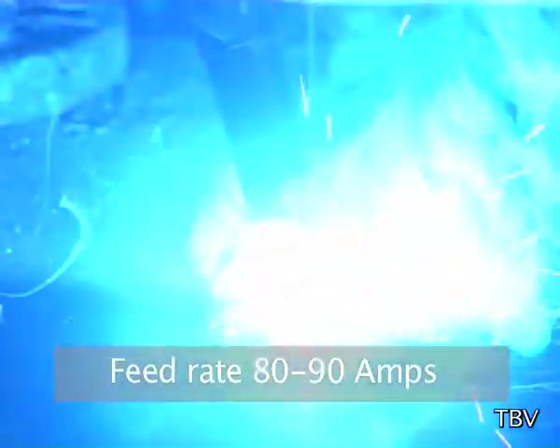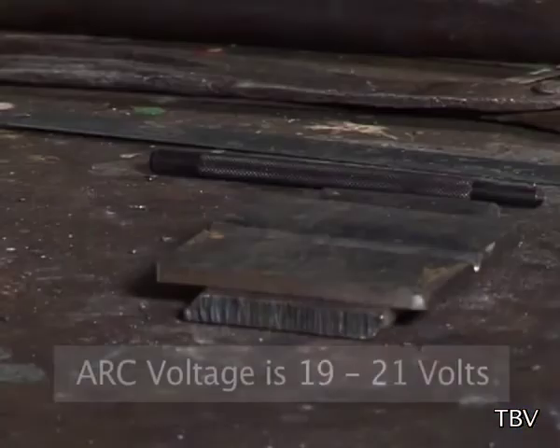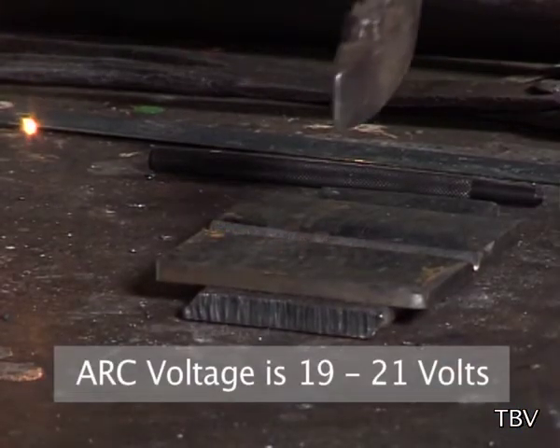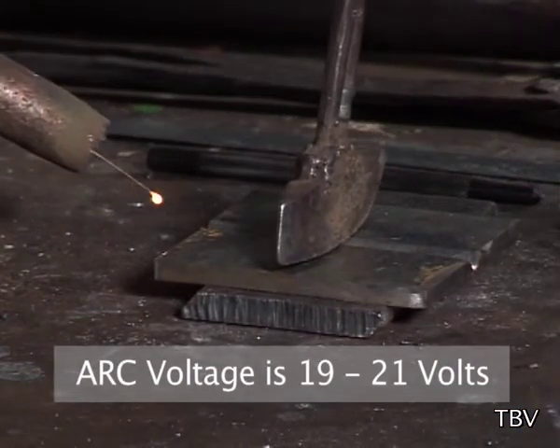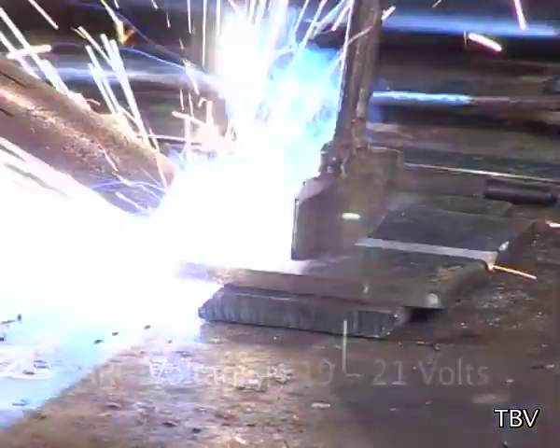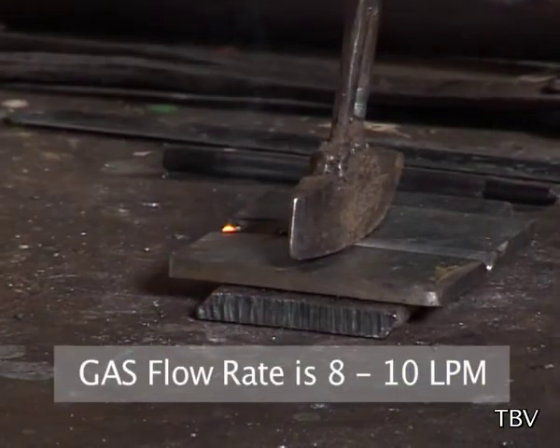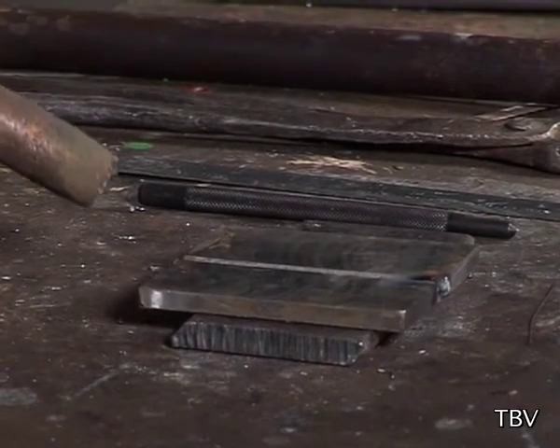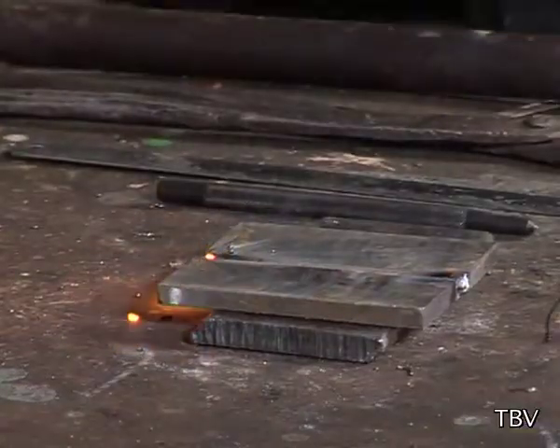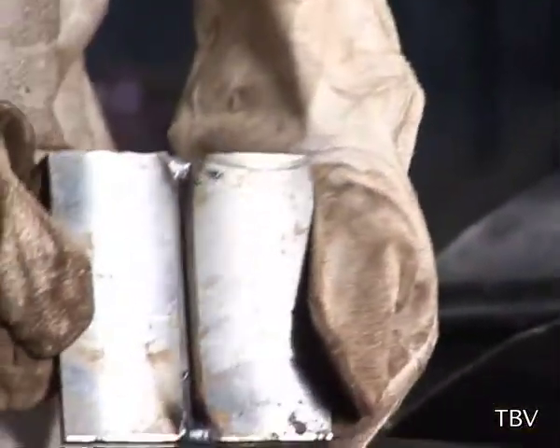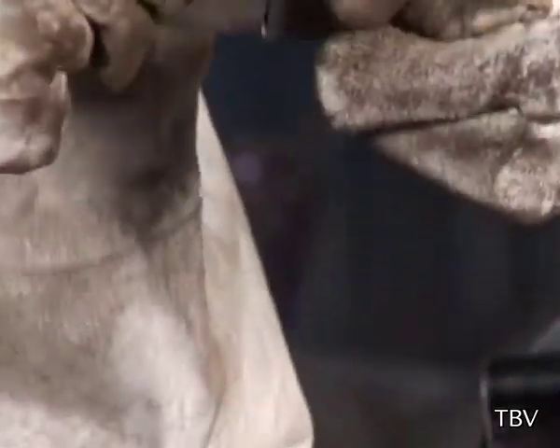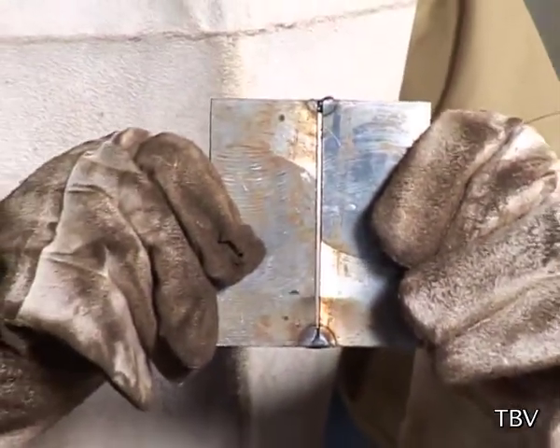Set the feed rate. The arc voltage is set at 19 to 21 volts as required for dip transfer mode. The gas flow rate is set at 8 to 10 LPM. Hold the gun perpendicular to the joint and strike the arc at the tack. Keep a gap between the joints, otherwise the job may get attached to the base.